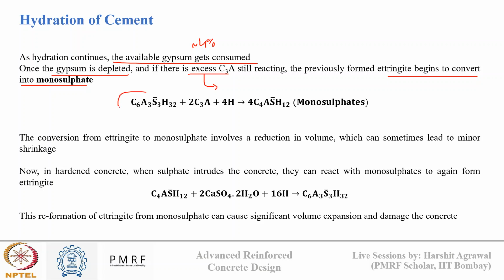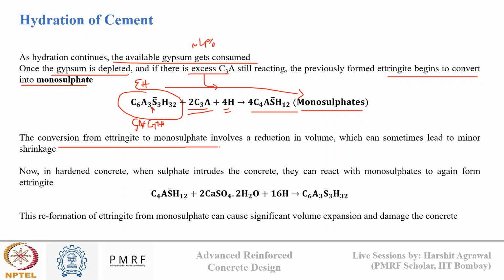So if you see, this is the ettringite which was formed due to the reaction of C3A and gypsum in the presence of water. Okay, ettringite was formed, and if there is excess C3A still present in the system and there is water present in the system, this ettringite will convert into this compound C4ASH12, which is known as monosulfate. And this conversion of ettringite to monosulfate involves